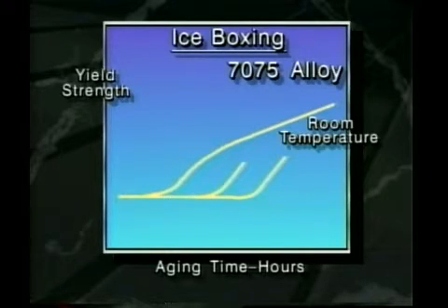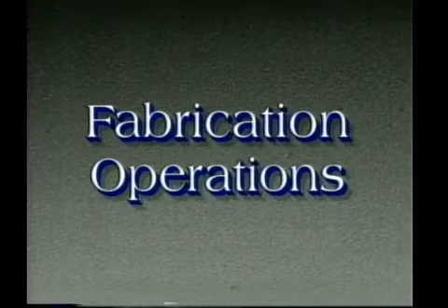At room temperature, the alloy starts to age about 1/2 hour after the quench. If the temperature of the quenched part is lowered to 0 degrees, aging is retarded so that a strength increase does not begin to occur until approximately 1,000 hours has elapsed.